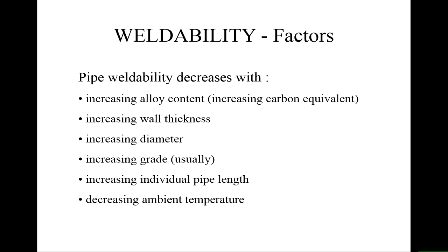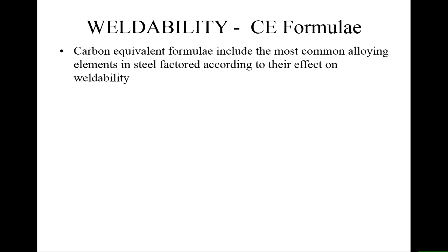If you increase an individual length of pipe from 12 to 18 metres as delivered, there's more metal to conduct the heat away, the weldability goes down. And if you decrease the ambient temperature, so you're welding in a Scottish field in the middle of winter, the weldability goes down. So anything you do to increase productivity and to make the process look nice and simpler and easier tends to make it more difficult to weld. And so you have to think about these things.